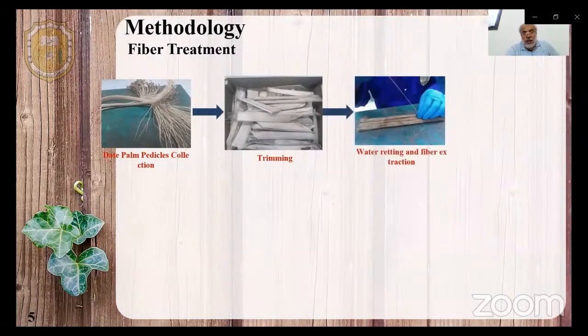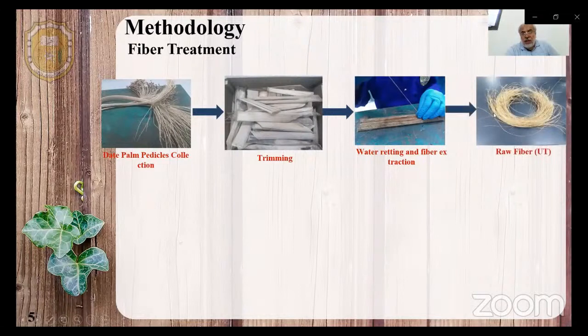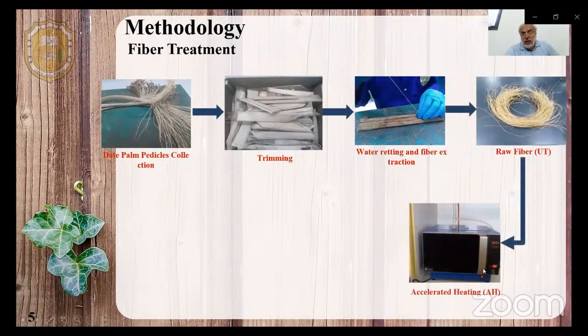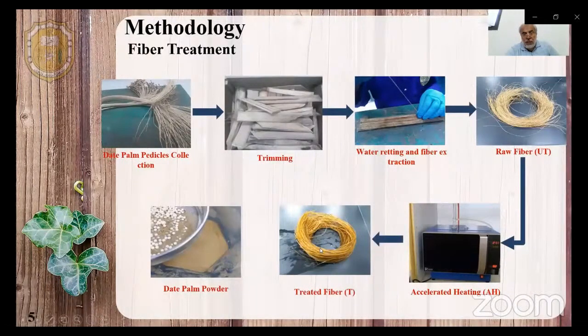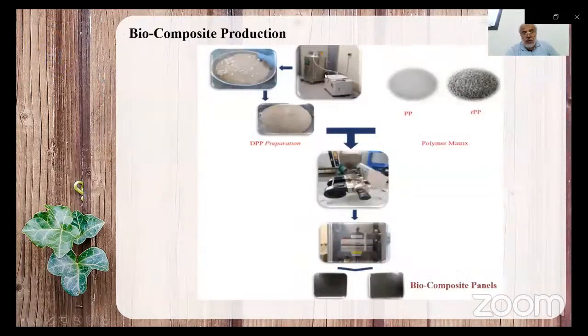For the fiber treatment, we take the waste of the date palm pedicel, and then we trim it to smaller pieces, and then we put it in water for a certain time to be able to extract the fibers in untreated form. And then we use a developed method using accelerated heating, using microwave, to treat the fiber, and then we grind it into a powder form to be mixed with the PP pellets. Here we use the pulverizer to mix the PP and the powder form of fiber. DPP stands for date palm powder, for two forms of PP, virgin and recycled.